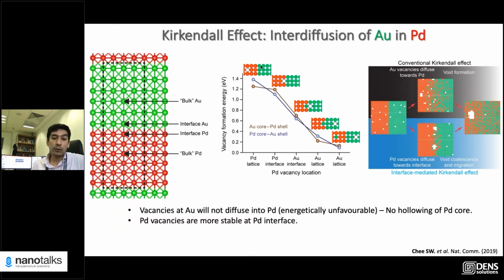So that's why you do not see movement of the vacancy from gold toward the faster diffusing species; it either hangs around at the interface or annihilates on the surface. But in the case of palladium, you actually see it forms at the interface, but then it continues and moves out to the surface and annihilates at the surface of the gold. So it can move because of this downward trend in the energy.